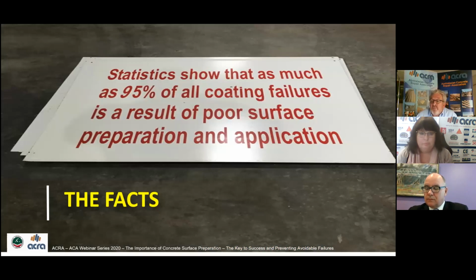ICRI, NACE, SSPC are all promoting the same fact, and that is 95% of all coating failures are due to inadequate surface preparation. Now, that can be not just inadequate surface preparation, it can also be application procedures. They might want to mix product with a stick because they didn't have a mixer, but 95% of failures come out of surface preparation and application.